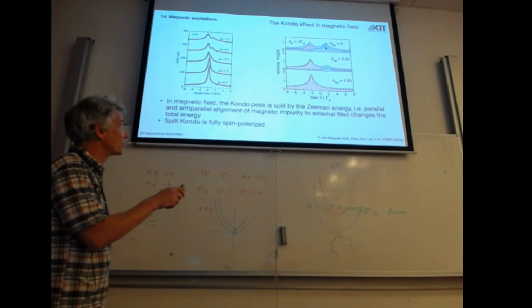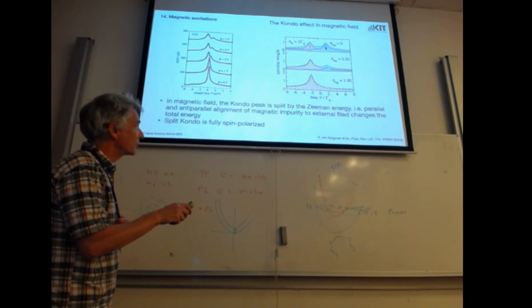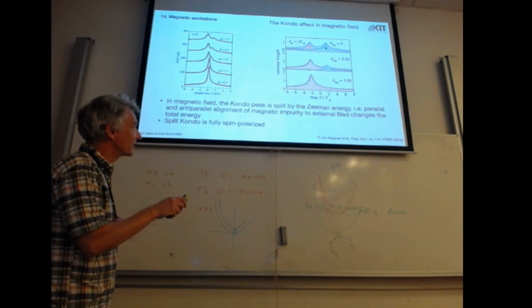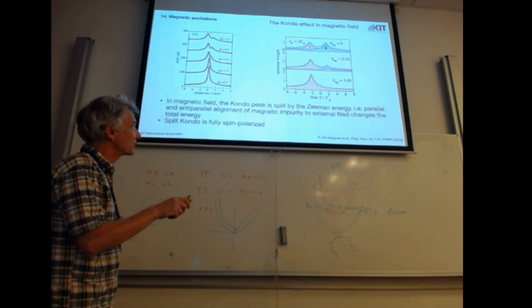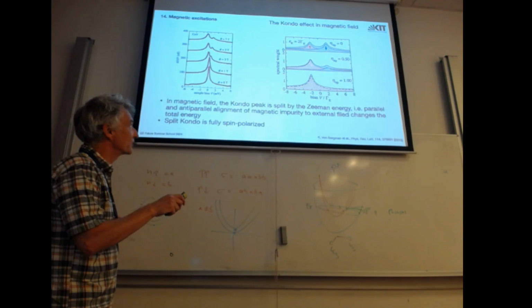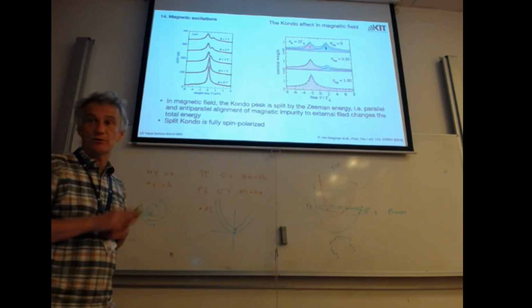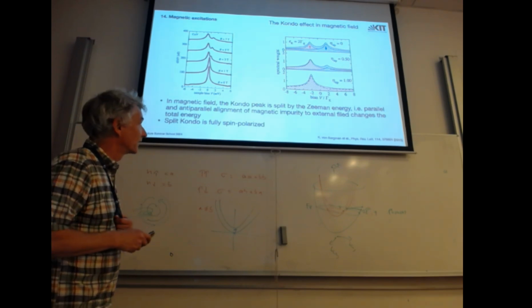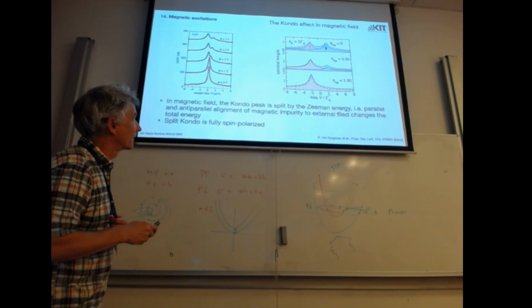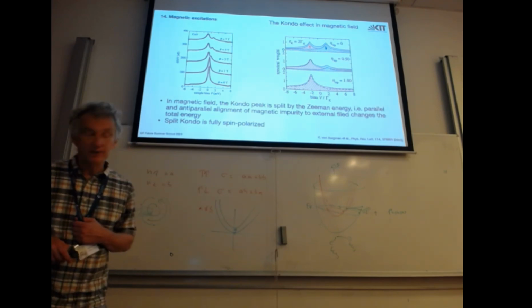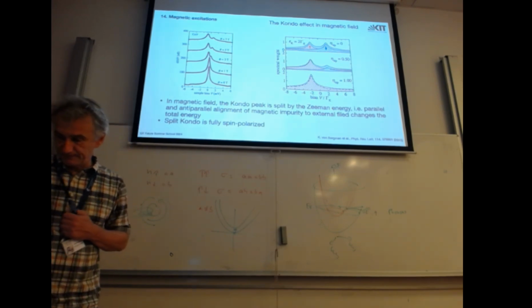So if you observe this with STM, if your tip spin polarization is full, you only see the occupied one. If you reduce the spin polarization, you can see two peaks. If the spin polarization of your tip is 0, you see two peaks. And I think the gray one is experimental data, the rest is theory.